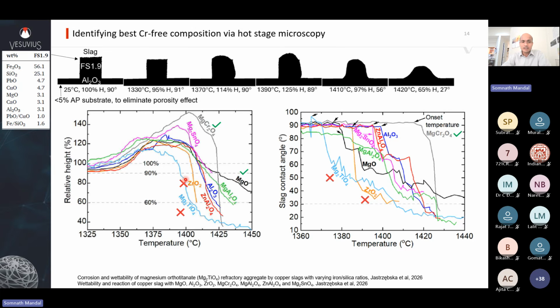And from there, we studied a lot of these substrates versus the same slag. And you can see that with magnesium titanate and zirconia, the slag melts very fast. That means that these are not corrosion resistant. On the other hand, you see magnesia-chrome and magnesia. Magnesia-chrome starts a lot later, and then magnesia always starts early. It continues to a higher temperature. This is the contact angle at the interface, and you can see that again, for magnesia-chrome, the reduction in contact angle happens at a much later temperature.